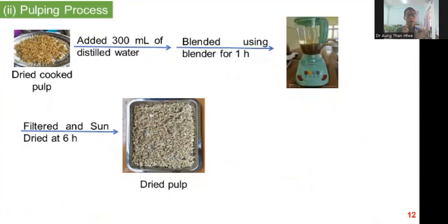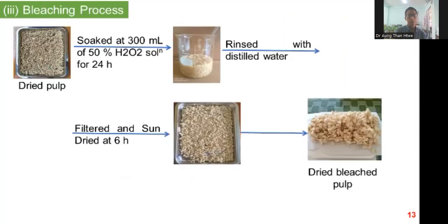The second step is the pulping process. The dried cooked pulp was added to 300 mL of distilled water and blended using a blender for one hour. After that, it was filtered and sun dried for 6 hours. The third process is the bleaching process. The obtained fine paste was soaked in 300 ml of 5% hydrogen peroxide solution for 24 hours, then rinsed with distilled water until neutral, filtered, and sun dried, and fine bleached paste was obtained.